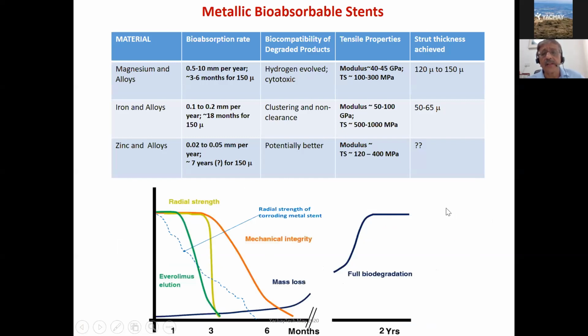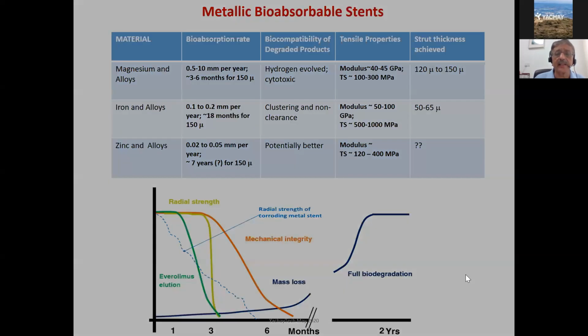So I'll just summarize the work here by showing the problems with the absorbable stents. So the radial strength has to be maintained for at least 3 to 6 months, and then they can slowly start to degrade, while the tissue coverage starts to happen at about the same time and must be fully developed by 12 to 18 months. In the meantime, the radial strength is decreasing. For fully degradable metal stents, it's decreasing faster than it is for polymers, which have this bulk degradation mechanism. So more difficult to control the mechanical properties for fully degradable metallic stents. But people are working on this, so there is hope that low strut thickness stents can be developed and tested in the clinic very shortly.